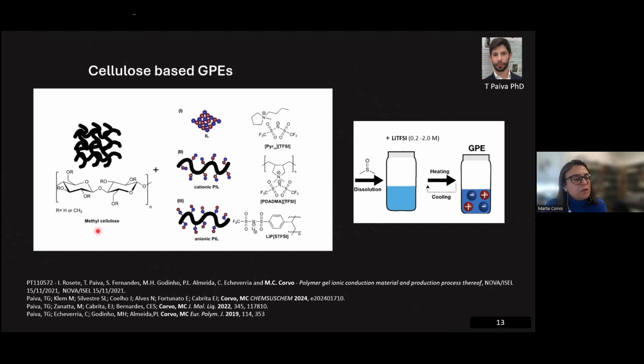And so we turn to either functionalizing cellulose or to its derivatives, in this case methyl cellulose, that is more soluble. In this work, we have mixed methyl cellulose with other ionic liquids. You can see here pyridinium bistriflamide. In another type of gel polymer electrolyte, we did the mixture with a cationic polyionic liquid, also a derivative from pyridinium and bistriflamide, but now in a polymeric version, where the backbone is the cations. So it's a cationic PIL. And we did also this version of the polyionic liquid that is anionic, where we put the negative charge in this backbone, the anionic PIL.